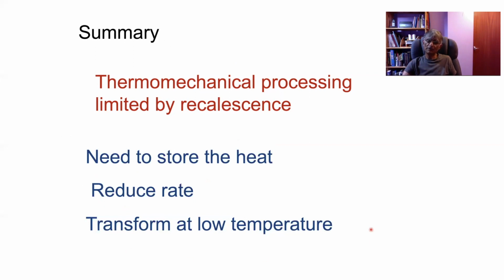And transforming at a low temperature is always a good thing because it increases the nucleation rate. I mean, that's an exaggerated statement because if you go too low, you might actually decrease the nucleation rate. But generally speaking, you will get finer structures when you transform at a lower temperature.